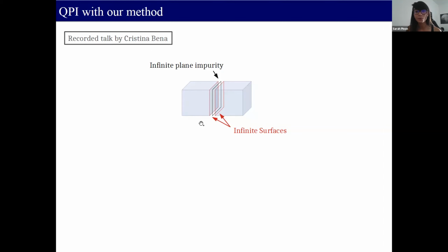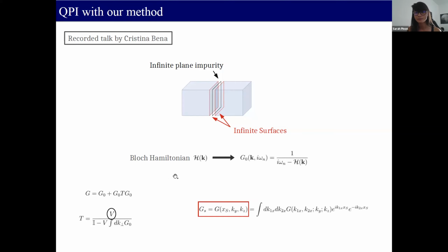These surfaces are parallel to the plane impurity. Now, if I describe my original system with the Bloch Hamiltonian H, I can then obtain the unperturbed Green's function which corresponds to it. And then from the equation I showed you earlier, I can compute the Green's function for the whole system, so now my system plus the impurity. Again, we have a T matrix where this time V corresponds to the plane impurity we have added.